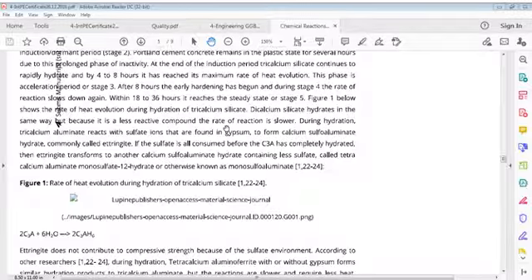Now dicalcium silicate hydrates in the same way, but because it is a less reactive compound, the rate of reaction is lower. During hydration, tricalcium aluminate reacts with sulfate ions found in gypsum to form calcium sulfoaluminate hydrate, commonly called ettringite. If sulfate is all consumed before C3A has completely hydrated, then ettringite transforms to another calcium sulfoaluminate hydrate containing less sulfate, called tetracalcium aluminate monosulfate 12 hydrate, otherwise known as monosulfoaluminate.